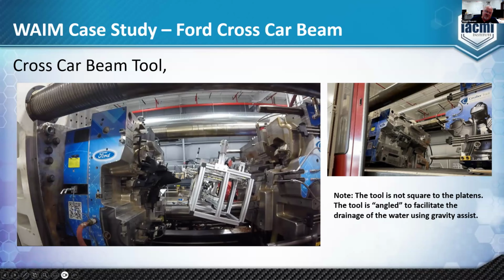The water inject system was in this location, and water entered the part through this channel. You'll notice that the tool is not set square to the platens of the press, and this was a 3,000-ton Milacron press that was used to make the part. It was not square to the platens. It was angled to allow us to use gravity assist to drain the water during screw retraction, and that facilitated water removal.